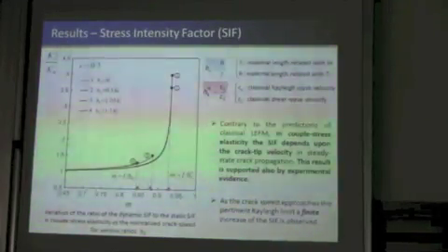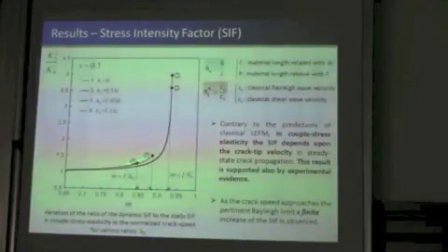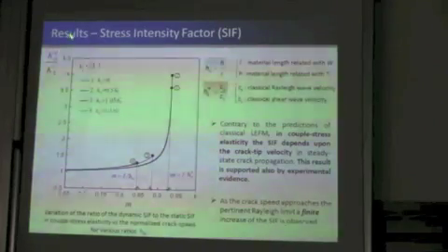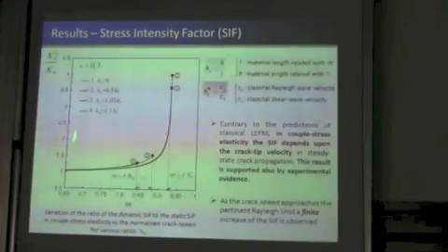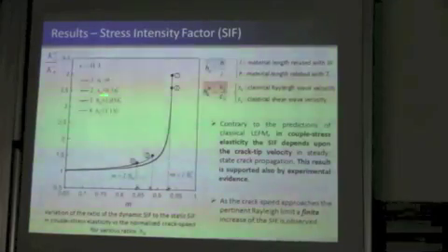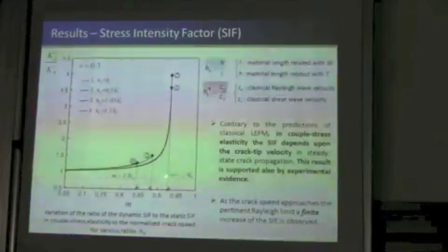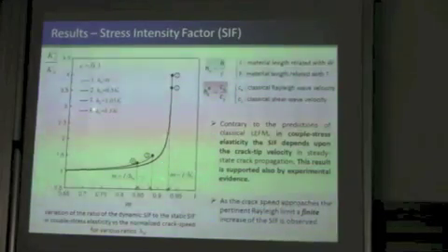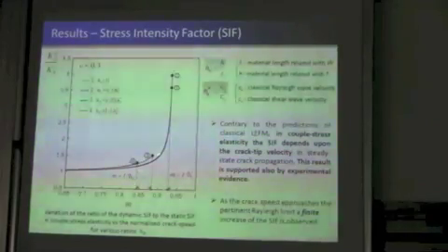Okay, here we see the variation of the dynamic stress intensity factor normalized by the static stress intensity factor. What we see here is that as the crack approaches the Rayleigh limit, we again have a significant increase, and we see that cases 1 and 2, which correspond to an H0 smaller than H0 star, end at the classical Rayleigh limit. However, when H0 is greater than H0 star, curves 3 and 4, the curve stops earlier, since this is the new Rayleigh limit, the coupled stress limit, which is less than the classical one.